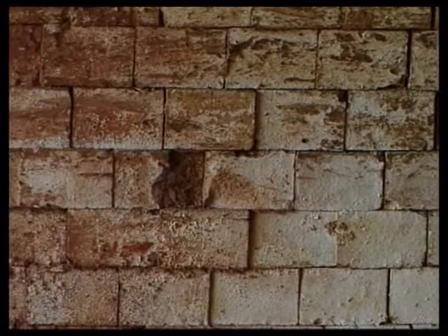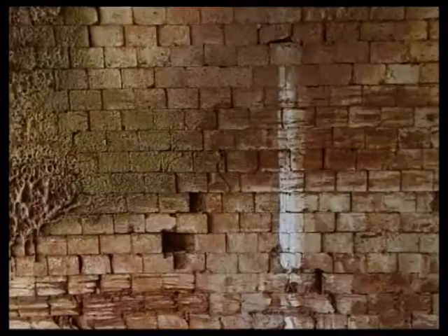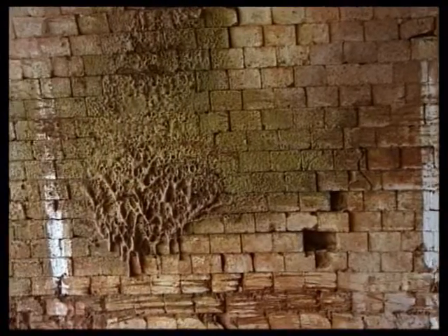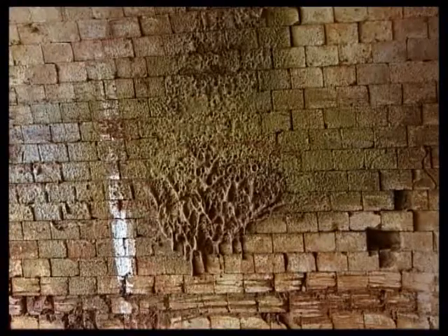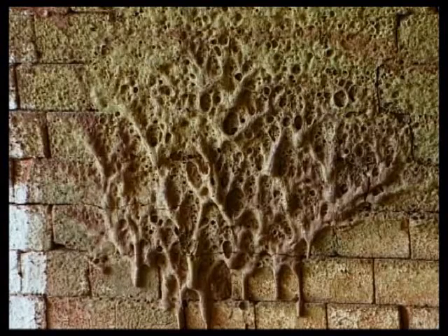bricks very well. But the bricks from which the kiln itself is made are rather special bricks, and they're refractory bricks made to withstand the intense temperature that is reached within the kiln and is processed many times over. They're put together without mortar because mortar wouldn't survive the great temperatures, so they're put together dry jointed, as it were, in these arch formations. And indeed, some of the bricks themselves have melted in the extreme temperatures reached in parts of the kiln.